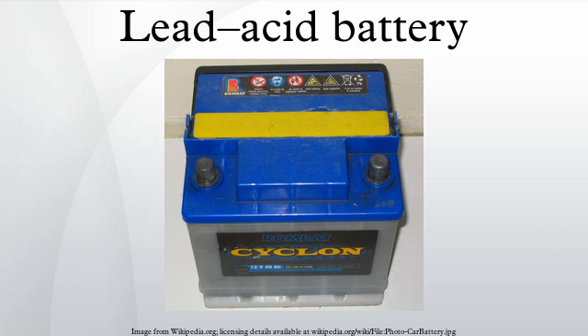Corrosion problems. Corrosion of the external metal parts of the lead-acid battery results from a chemical reaction of the battery terminals, lugs and connectors. Corrosion on the positive terminal is caused by electrolysis, due to a mismatch of metal alloys used in the manufacture of the battery terminal and cable connector. White corrosion is usually lead or zinc sulfate crystals. Aluminum connectors corrode to aluminum sulfate. Copper connectors produce blue and white corrosion crystals. Corrosion of a battery's terminals can be reduced by coating the terminals with petroleum jelly or a commercially available product made for the purpose.